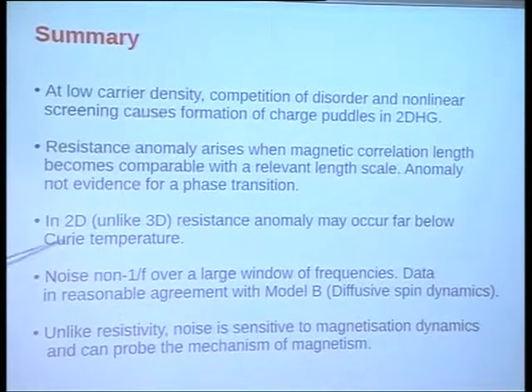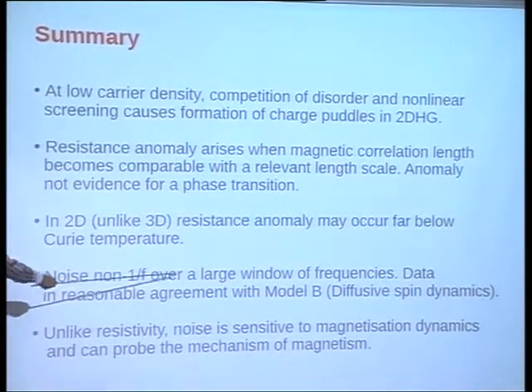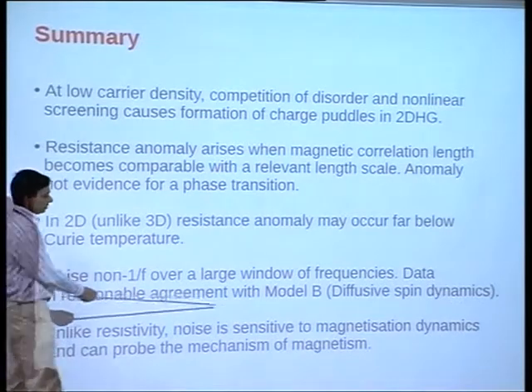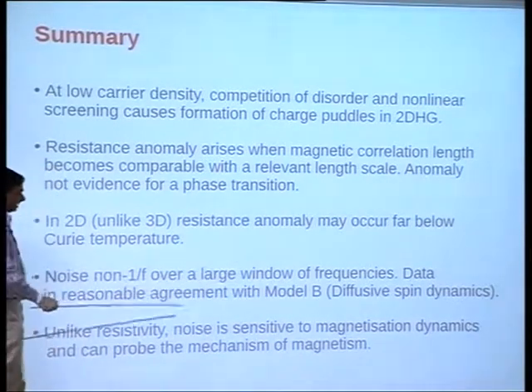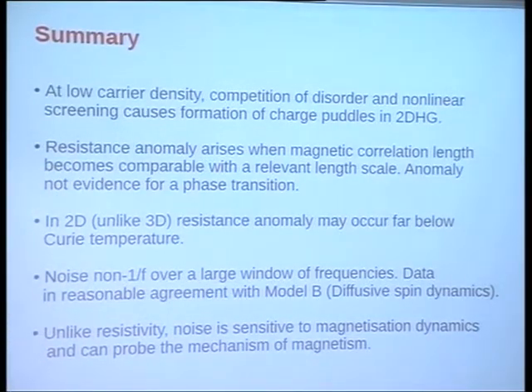In 2D, the noise is non-1 over f over a large window of frequencies, and very phenomenologically it's in reasonable agreement with conserved or diffusive spin dynamics of a Heisenberg ferromagnet. And unlike resistivity, I showed you how noise is sensitive to magnetization dynamics and can probe into the mechanism of ferromagnetism. Thank you.